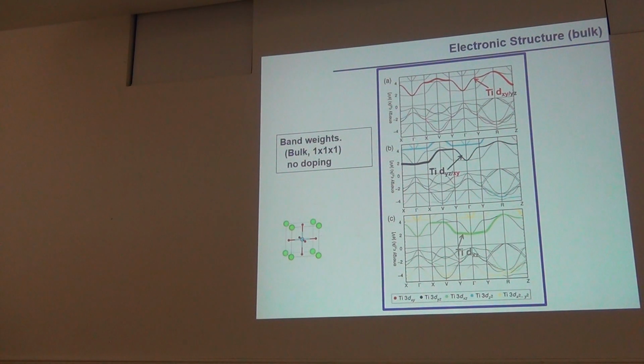Now in this system, because in strontium titanate all the d electrons of titanium are unoccupied, this is what we see. And what I'm plotting here in heavy is the weight of the three t2g orbitals. Okay, so far so good. Yep. It looks like a narrowband metal at the R point. At the R point, here. It looks like a narrowband metal. So, good, very good observation.